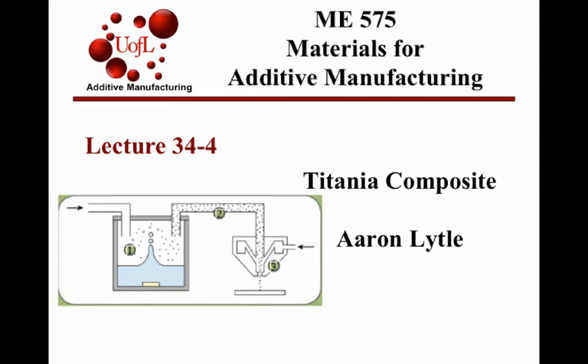Titanium-based ceramics. This picture is a picture of the 3D printing process they used in this paper. It's an aerosol-based printer. So in the big box with the little one, that's your polymer titania composite liquid, and they just use a high-pressure gas to aerosolize it. So it's then carried through a pipe and transferred to a nozzle, and then a second gas focuses it and pressurizes it so that it deposits on the surface.